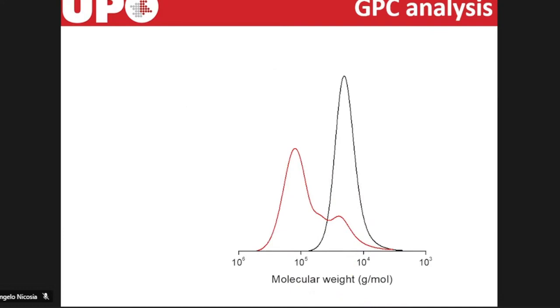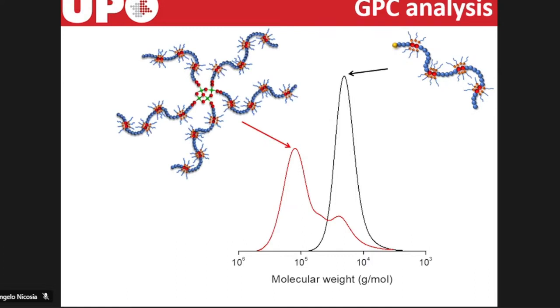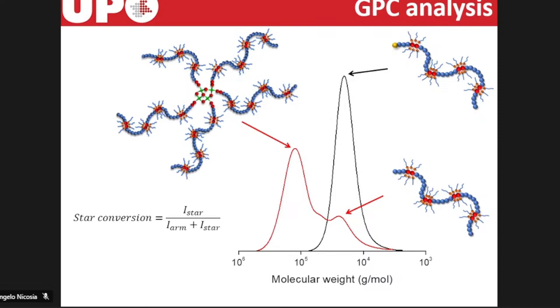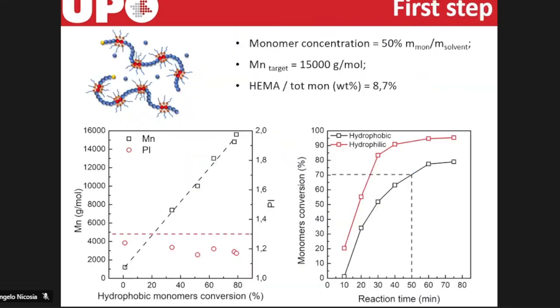Through GPC analysis, we can observe the formation of a star copolymer. In particular, at the end of the first step, we have a narrow weight distribution peak at a low molecular weight. And at the end of the second step, we can observe a second peak related to the formation of star copolymer. Using this technique, we can calculate star conversion and the number of arms.